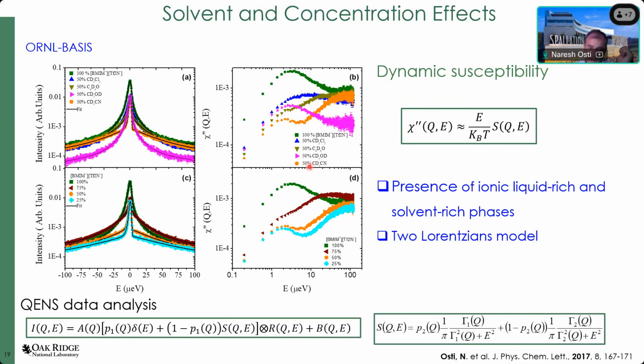But if you look at the concentration dependence, there is a significant change in the low energy transfer peak. This blue one is coming from the pure ionic liquid, and the others are in the presence of acetonitrile. You can see that this peak position changes significantly when you change the concentration of the organic solvent. It means that the low energy transfer peak is coming from the ionic liquid rich phase, and the high energy transfer peak is coming from the solvent rich phase, which is the organic solvent rich phase.